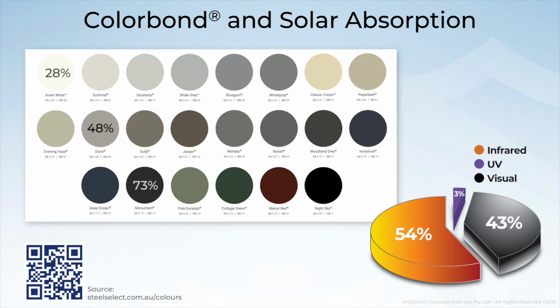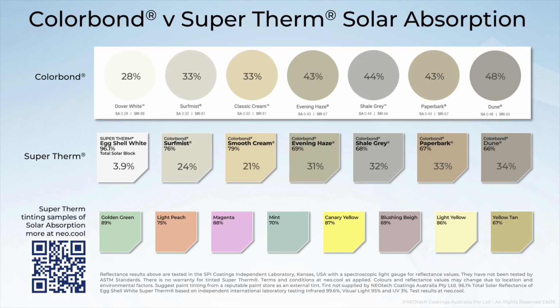And even if we were to look at ColourBond's solar absorption rates, their lightest colour, Dover White, has a solar absorption around 28%. So they're still a long way off being able to stop the infrared heat. And unfortunately, when you look at the darker colours of Monument, Night Sky, it was a ridiculous amount of heat being pulled in, because we do know that visual light is 43%. So the lighter the colour you go, the less visual light you will absorb. But if we compare Supertherm with ColourBond, similar colours, our Surf Mist comes in cooler, and it goes on and on from there. So you can see the major difference by blocking heat. It's still drawing the heat in visually, however, blocking the heat makes a major difference.